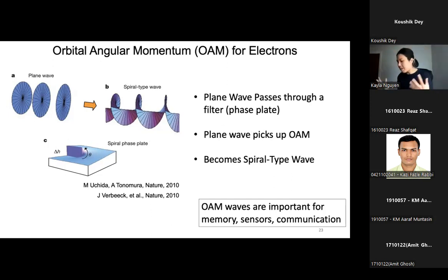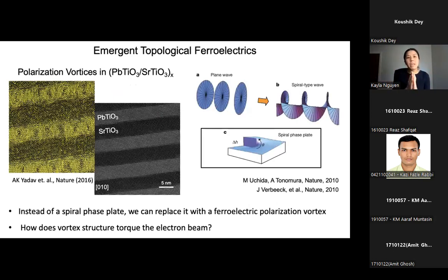So now if we think about imaging orbital momentum in the electron microscope, we can think about taking an electron, putting it through something, and getting torque from that information. Instead of having a spiral phase plate, what if we have a topological ferroelectric? For example, polarization vortices in lead titanate, strontium titanate. This is a sample that has gained a lot of interest recently, where you take a layer of lead titanate, particularly 10 to 12 unit cells, and stack it on top of 10 to 12 unit cells of strontium titanate. Because of the energetics of the system, it forms these polarization vortices.